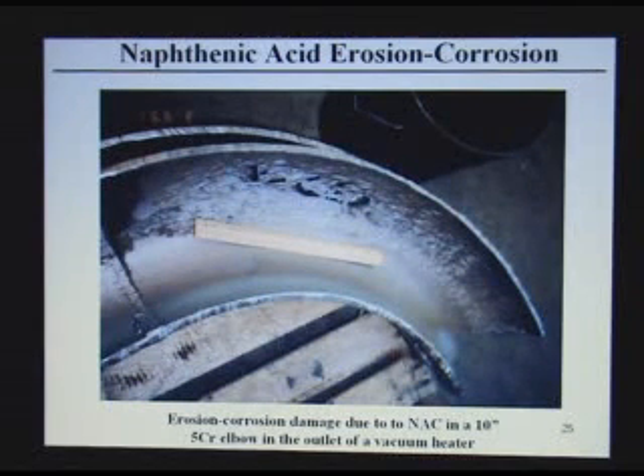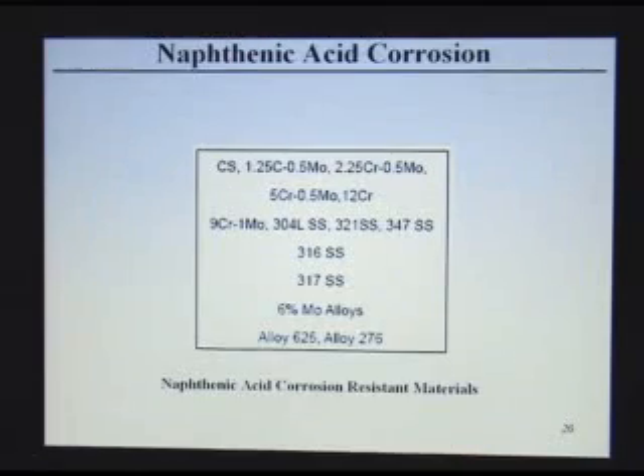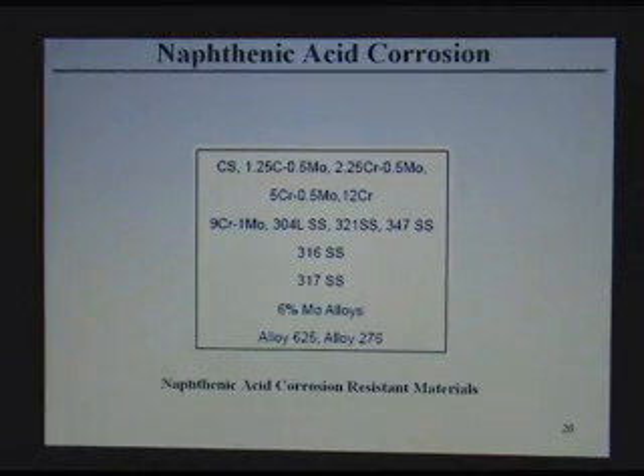Naphthenic acid forms some very loose corrosion product, and if you have flow impingement, it goes very fast, and this is typical for naphthenic acid corrosion enhanced by stream flow. I found this interesting: naphthenic acid corrosion resistance is determined by molybdenum content. The more molybdenum, the more resistant the material is. And of course, these are not resistant at all. It's a very small amount of molybdenum.